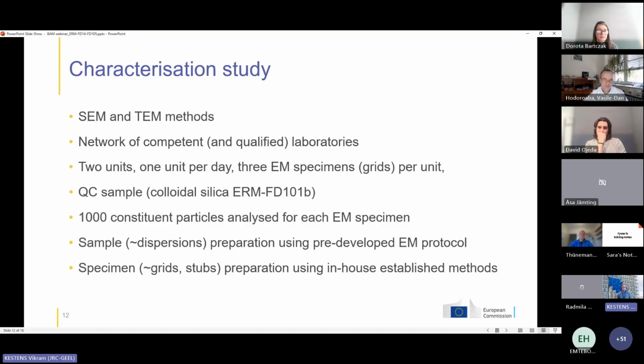Then again, going to the characterization, we used the electron microscopy methods, scanning and transmission electron microscopy, and the characterization was done by a network of competent and preliminary qualified laboratories that adhered to the principles of the ISO 17025 standard. Just to give you an idea, we invited about 14 expert laboratories to participate in the study. But in the end, only 4 laboratories were able to do so, because these were the only ones who had the measurement of powders in their scope.